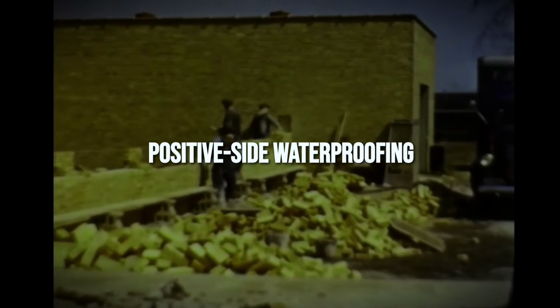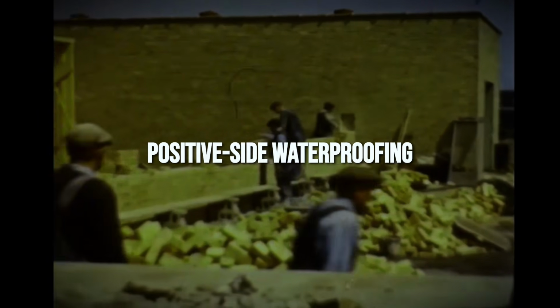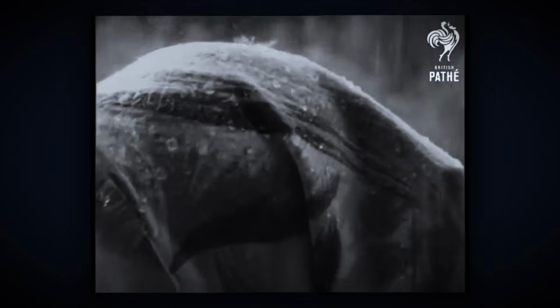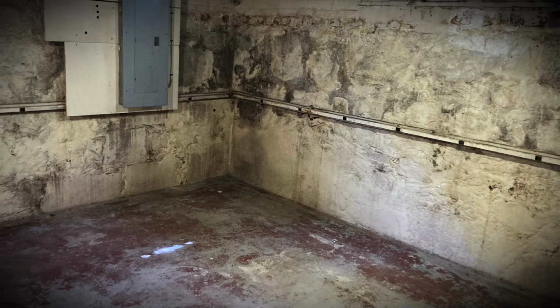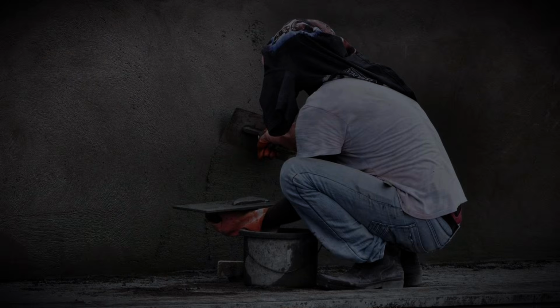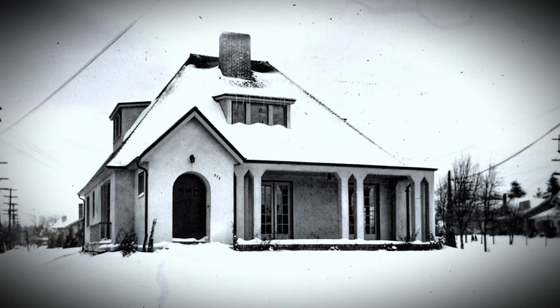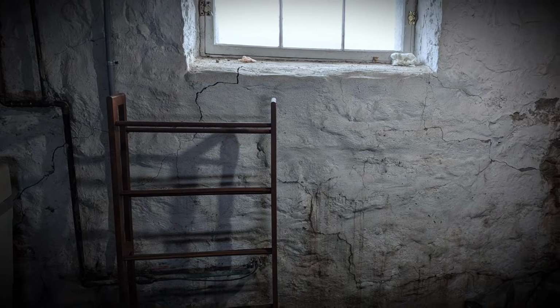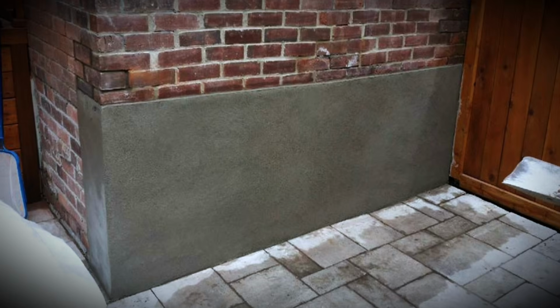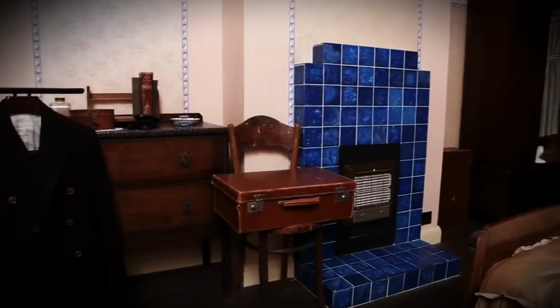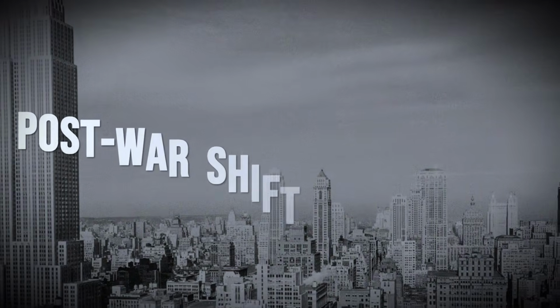Together, these 2 layers created what engineers call a positive side waterproofing system. The water was stopped on the outside of the wall before it ever had a chance to reach the interior. And because both materials were rigid but slightly flexible, they could handle the normal expansion and contraction that concrete goes through during freeze-thaw cycles without cracking or delaminating. If you have ever been inside the basement of a well-built home from the 1940s, you already know what this looks like in practice. The walls are dry. There is no efflorescence, no staining, no musty smell. The system just works. So what changed?